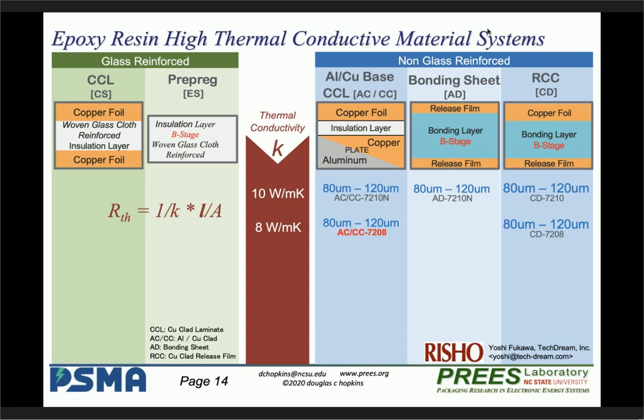When it comes to aluminum nitride, we can't compete. So if you walk in the lab and say, hey, Doug, what should I do? Well, if this is really high performance, you need aluminum nitride. It's going to be a metal clad ceramic, and of course, aluminum nitride or silicon nitride, it's going to be metal clad ceramic. Now, if you're saying, I need something lower cost, and that's the big key, something lower cost, and I want to have it lighter, what do we have? Well, here's the organic approach. If you could have done it with aluminum oxide, alumina DBC, this would be a better approach, particularly because the organics give you much higher reliability because the modulus is so low. And keep in mind, this is the thermal equation. It's the thermal conductivity times the length, and that's the length of the path that the heat goes through.